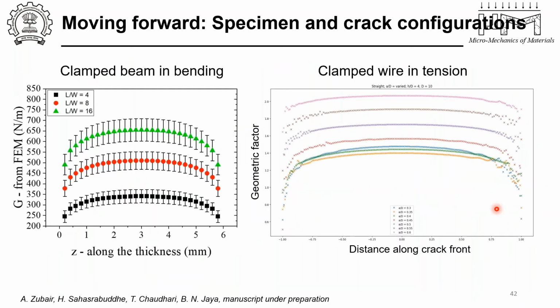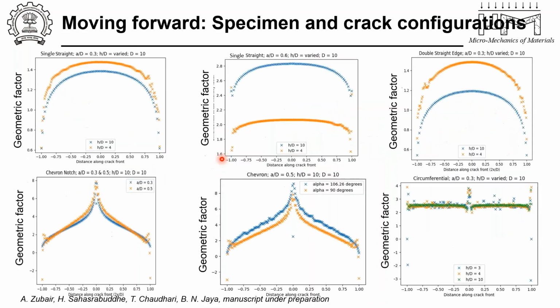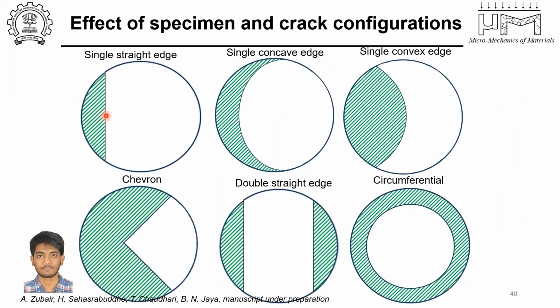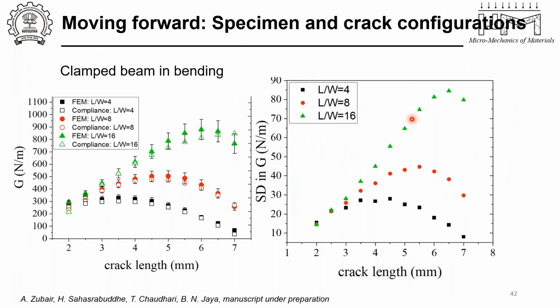This I will skip, but I wanted to say that the position along the notch tip also matters, and you can predict in which way the crack would grow for different configurations. For example, for this particular specimen, the stress intensity factor happens to be highest here compared to here, so the criticality is reached here first. So a straight edge sample would convert to what is called a convex edge sample. If you do a fatigue pre-cracking, then this is how it would look. Then again, whether you can use the geometric solutions of this or should go for this, and so on. So the nitty-gritties of that are also being explored.